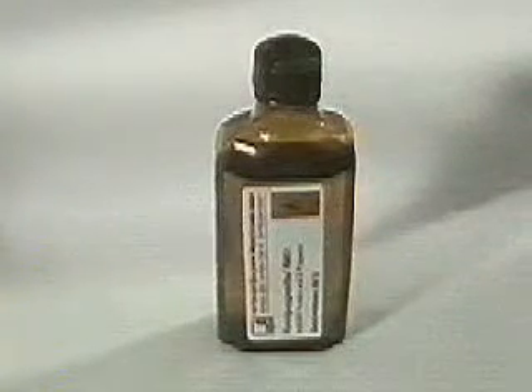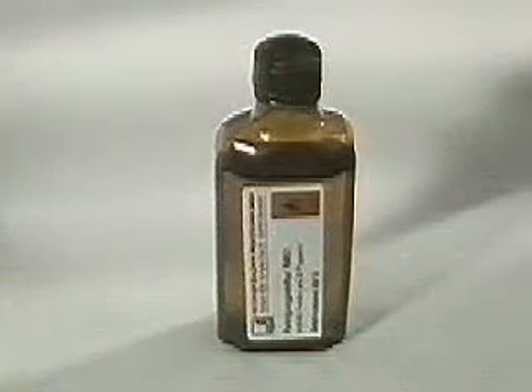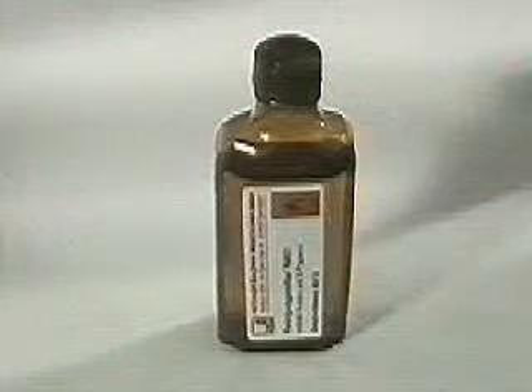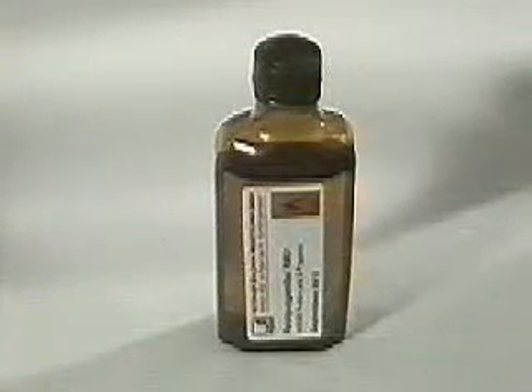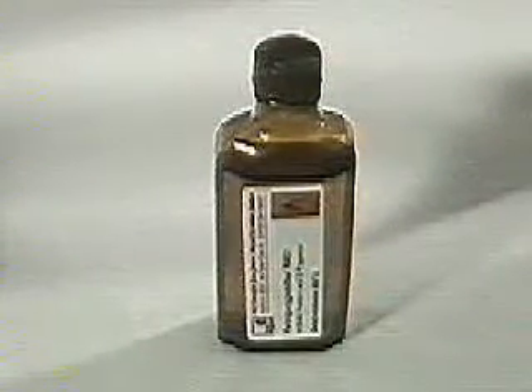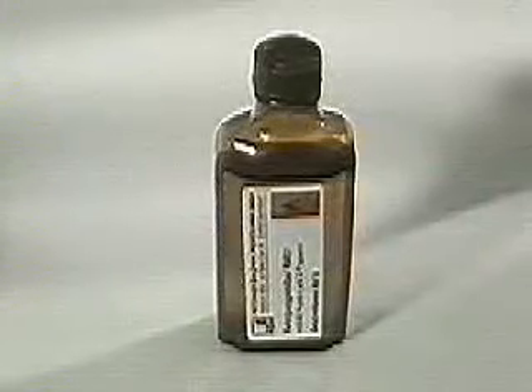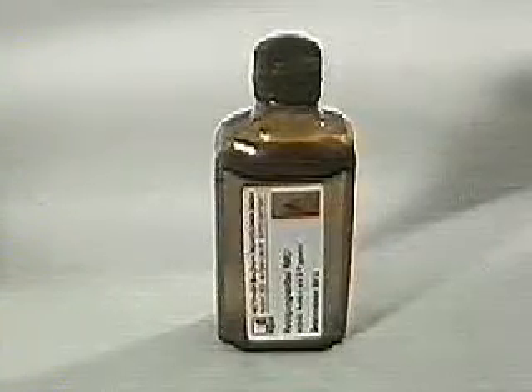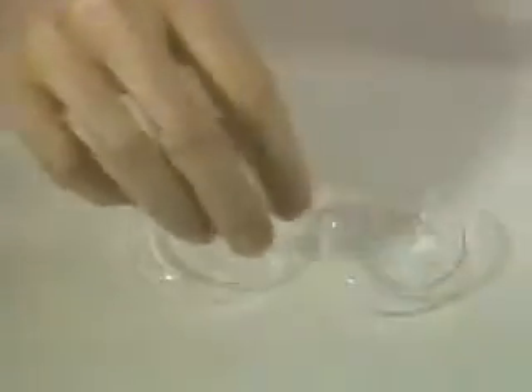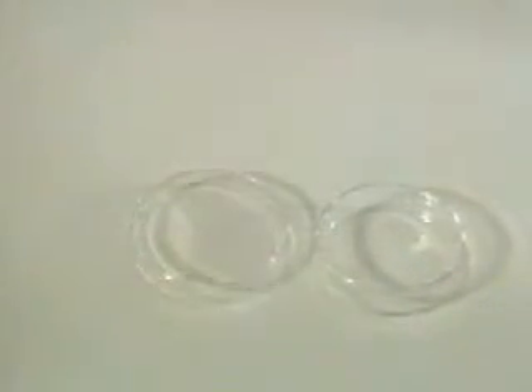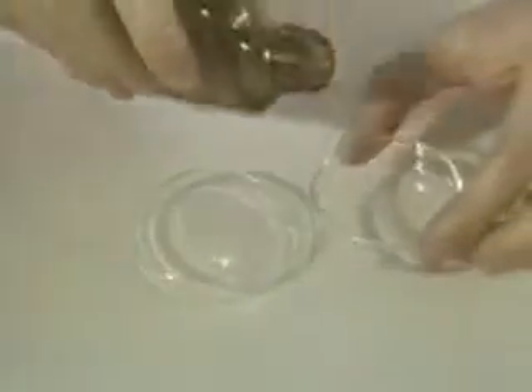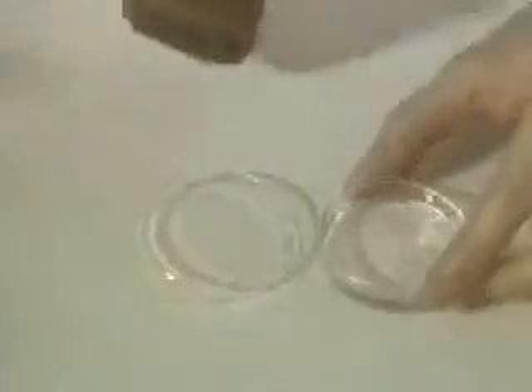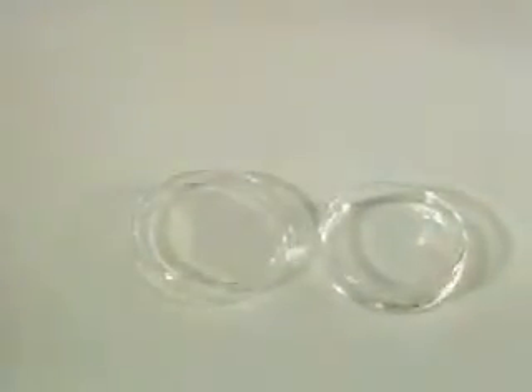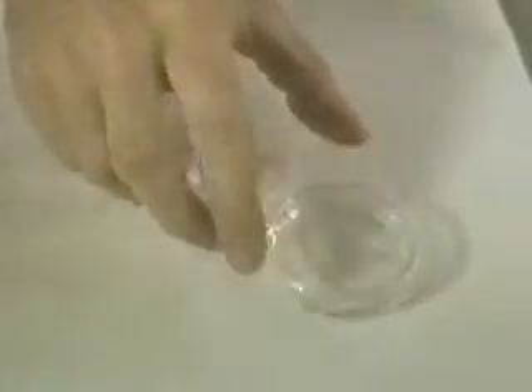The abraded metal and contamination are removed with an extremely pure solvent. To keep the solvent clean, the solvent is never used directly from the bottle, but instead a small amount is poured into a clean intermediate container. 2-part glass Petri dishes have proven useful for this task. The solvent is poured into the smaller dish and covered with the larger dish to prevent unnecessary evaporation. Any residues of solvent must never be returned to the bottle.